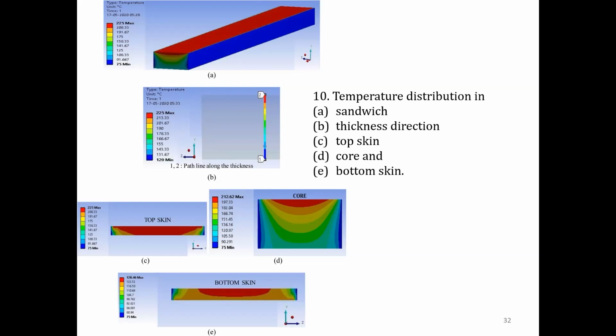Now, due to a sudden decrease in thermal conductivity at the skin core interface, because as I said, skin properties are different, core properties are different, there is something known as the stagnation effect that creeps in. It raises the temperature at the top layer and interface as compared to the first layer of the bottom skin.